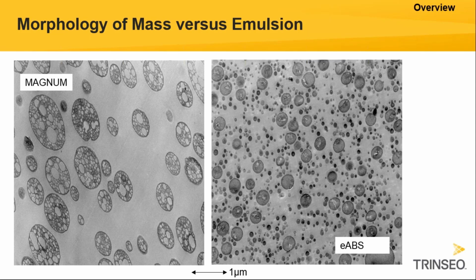On the right side, we have the emulsion ABS, and you can clearly see that the rubber particles are significantly smaller and they do not contain occlusions. In the emulsion polymerization process, there is a higher control possible on the rubber particle size. And hence it is also possible to produce smaller rubber particles in an emulsion ABS process compared to a mass ABS process. And for those applications that are seeking the highest gloss levels, they will have more benefits in using an emulsion ABS.